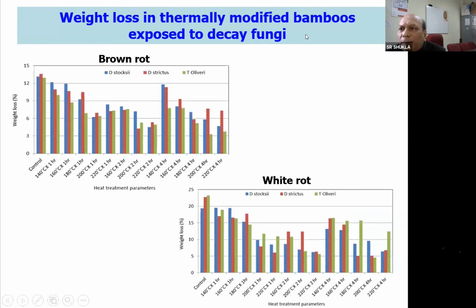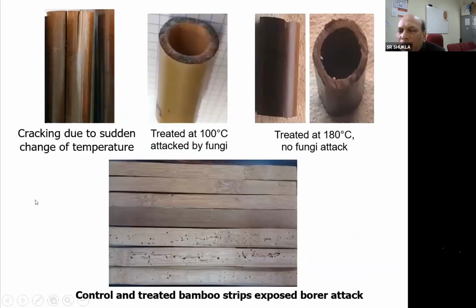And then this is the decay resistance of the treated bamboo, which will be improved against the decay fungi. This is brown rot and this is white rot. This shows the control bamboo, and these are the bamboo treated with different temperature and duration. So we can see here with this treatment, the amount of weight loss against the brown rot and white rot fungus will be less. This shows that this treated bamboo will not be attacked much by the fungus and borers.